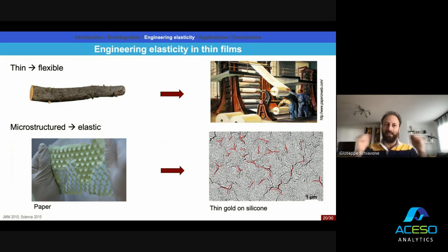So you can elongate the piece of rubber. The rubber is elastic, so it will elongate, of course. But now what happens to the gold is that because we have these cracks in the material, these cracks can expand. So when we elongate the rubber, the cracks in the gold expand, and the areas that are not cracked in the gold stay conductive. So we always have a conductive path connecting all the solid islands in the thin film gold.